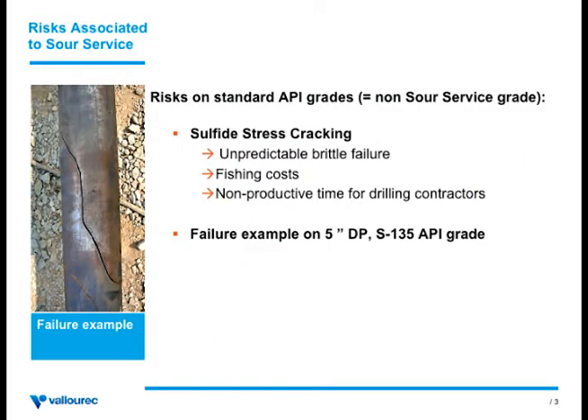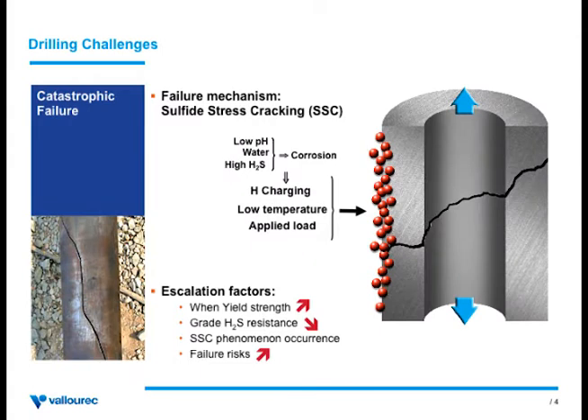You can see in the picture on the slide an example of an SSC failure. It's a very typical facet of failure where you have a 45-degree angle compared to the stress direction. So in the case of a drill pipe, you will have a 45-degree angle compared to the vertical direction. The particularity of the failure and the problem linked to H2S is that it will occur below the tensile capacity of the pipe. So you cannot really predict it. You cannot see any deformation of the material. It's very different from any other kind of failure mechanism you can have on drill pipe. So it's unpredictable.